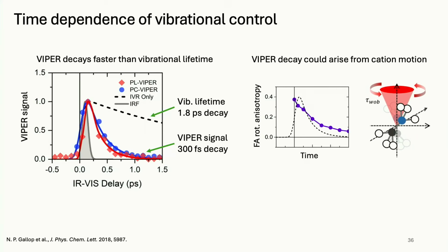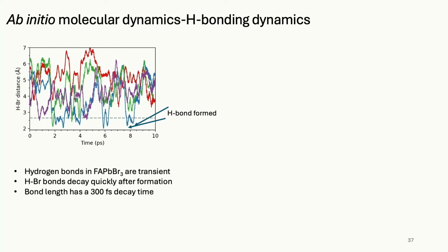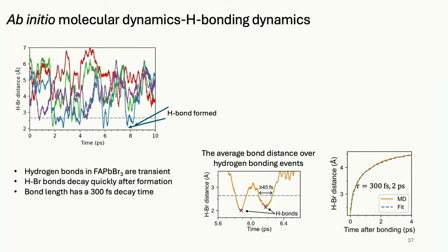And so what we're able to show is that if you have cation motion, so it's still vibrating, but if this guy rotates and breaks a hydrogen bond, then you lose the connection and the VIPER signal goes away. So we actually did a molecular dynamics study of this material, and we were able to just keep track of all the hydrogen-bromine distances. So lots of them are big, but then you form a hydrogen bond and it goes away. Then you form a hydrogen bond and it goes away. And in general, the lifetime of a hydrogen bond, wouldn't you know it, is about 300 femtoseconds. And so that's the lifetime. You excite the high energy vibration on the molecule, that keeps going, but the molecule rotates and breaks the hydrogen bond, so it's no longer talking to the lattice.